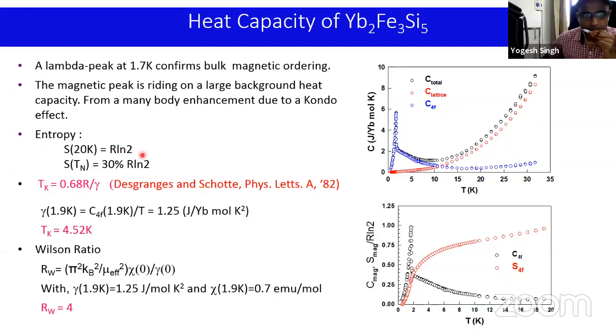So the entropy is R log 2 only up to about 20 Kelvin. So we seem to have an effective spin half, which is separated from the higher crystal field level. So we can worry about only spin half entropy. The entropy at the ordering actually is only 30% of R log 2, which means that most of the local moment is quenched already at higher temperature, and a very reduced moment ordering is happening at TN. These data can again be used to estimate the Kondo temperature, and we get from the heat capacity a Kondo temperature of about 4.5, which is similar to what we got from transport. These are anyway crossover scales, and therefore you won't get a sharp transition temperature like thing here. So 5 and 4.5 are the same for us.